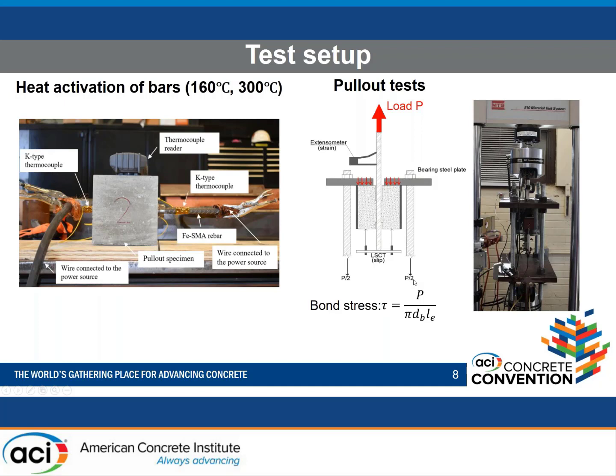For the setup, we are using a standard pull-out test. Here is a specimen, and here is the machine used, an MTS machine. As you can see, the bar is pulled out while the specimen is bearing on a steel plate. This steel plate is connected to another bottom steel plate, which is gripped at the bottom part of the MTS.